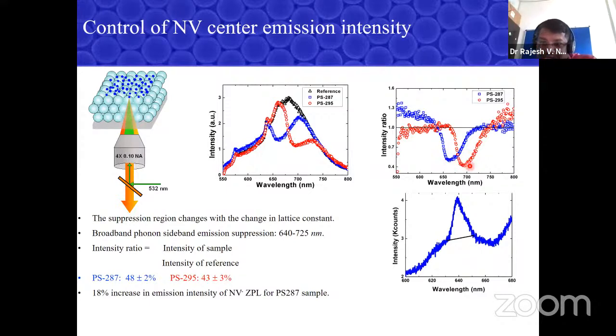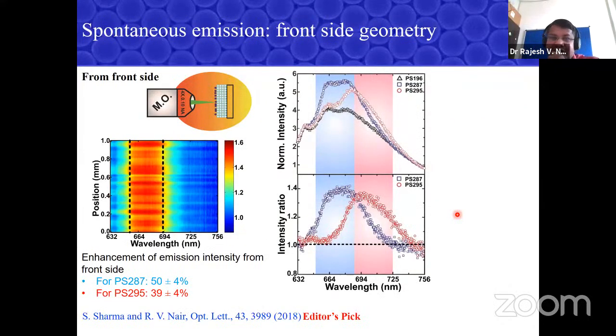And not only can I suppress the phonon sideband, if I do it very smartly, I can enhance the zero phonon line using the band edge effect of these systems. So this is one way to control the NV center emissions. You can change the geometry, you can measure from the front side. Not only suppressing, if you want to enhance the emission from NV centers, you can do that. And this is good in the cosmetic industry and bioimaging because you want more reflection, more light from diamonds.